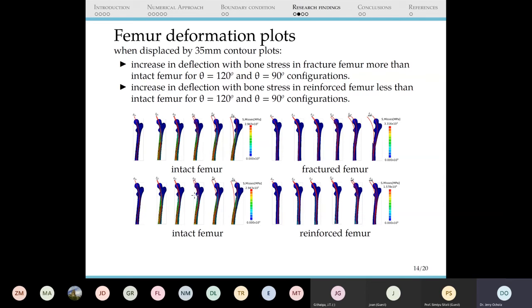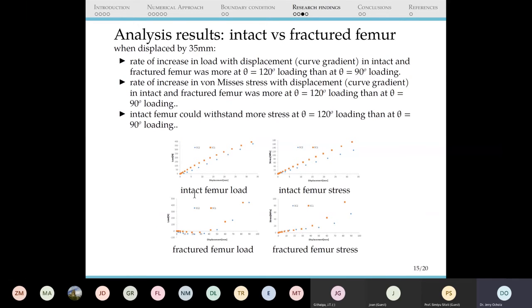The mechanical analysis illustrated that, comparing the intact bone, or the bone before the fracture, with the bone with the fracture, the rate of increase in the load displacement was more in the single stance, or theta equals 120 degree loading configuration, compared to the theta equals 90 degree loading configuration. Our results also show that the fractured bone had almost no resistance to loading, because of the fracture.